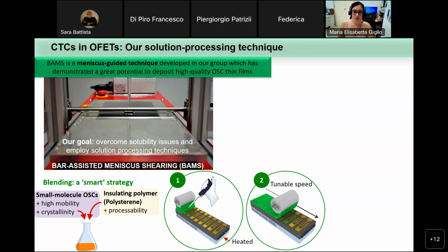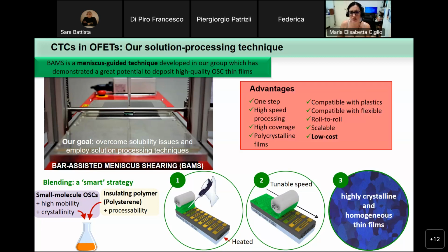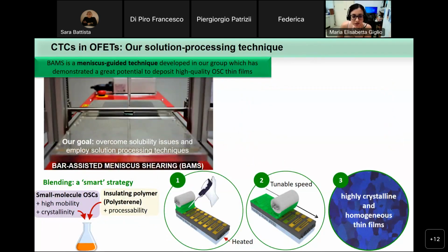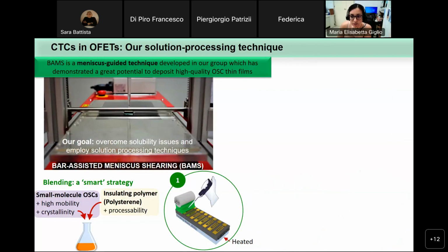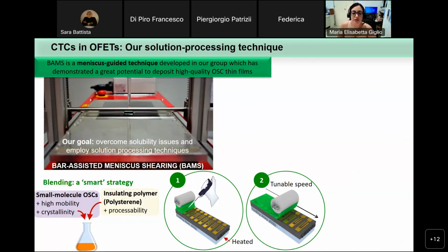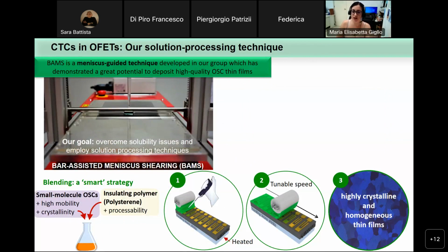After that, we start the movement of the platform. Okay, here there was a video that is not showing up. Okay, doesn't matter. So basically by the movement of the platform, we drive the crystallization of the film, because when we inject the ink, we create a meniscus, and then the meniscus drives the crystallization. So in the end, we obtain highly crystalline films and very homogeneous.